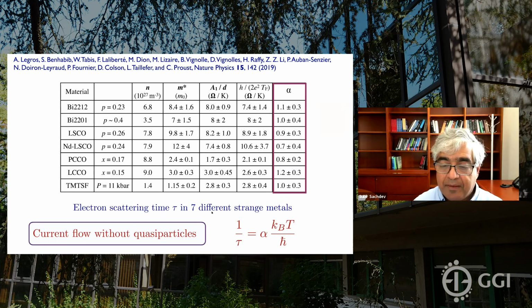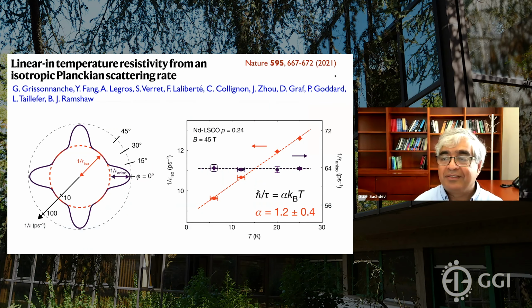Okay. All right, so here's another, very recent experiment, just published in Nature, where they've used a somewhat different method to measure the scattering time. And in this case, they can distinguish the scattering time of electrons going along different directions. What they find is that there's an isotropic piece, which doesn't depend on any of the details of the lattice structure. If you look at this isotropic piece, here's its temperature dependence: 1/tau, again a linear function of temperature with alpha close to 1.